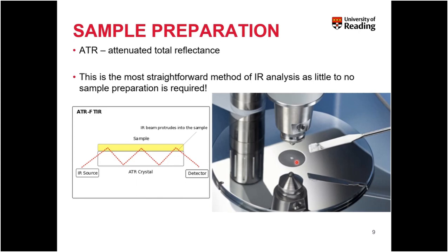You then take your sample, which you can see here, and place some of it on top of this crystal. If the sample is a solid, you will then use a pressure tower, which is this pointy bit above the plate, and you will screw this pressure tower down so that it compresses the solid sample into the diamond crystal. What then happens is the infrared spectrophotometer emits infrared light, and the infrared light bounces through the crystal, and some of that light is absorbed by the sample. The beam then goes back into the spectrophotometer and is passed to the detector.